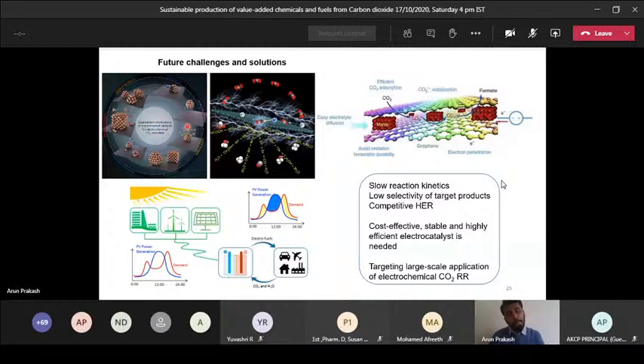The other main drawback is that multiple products are formed because it is a multiple proton and multiple electron transfer process. So selectivity is the issue. When you want to produce a C1 or C2 product, you have to control the proton and electron transfer. Another huge challenge is how we are going to get the energy to drive the CO2 process. Instead of a normal electrocatalyst, you can use a photoelectrocatalyst, use solar light as the source, shine it on your catalyst surface, and drive the CO2 reduction process using solar light.